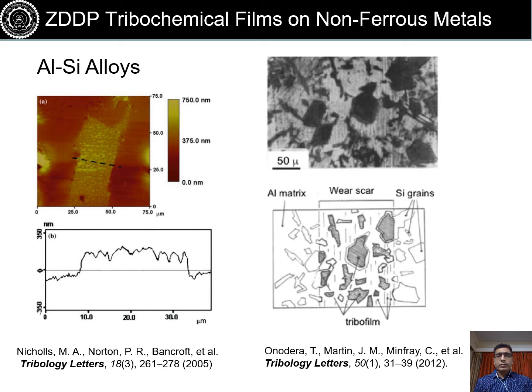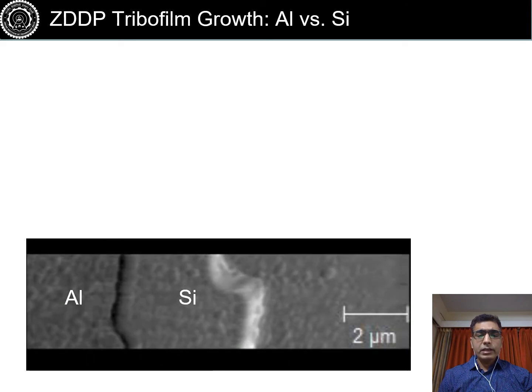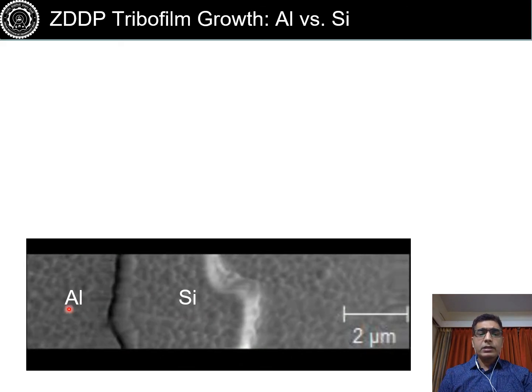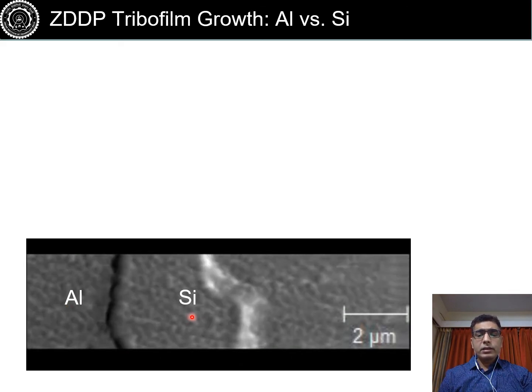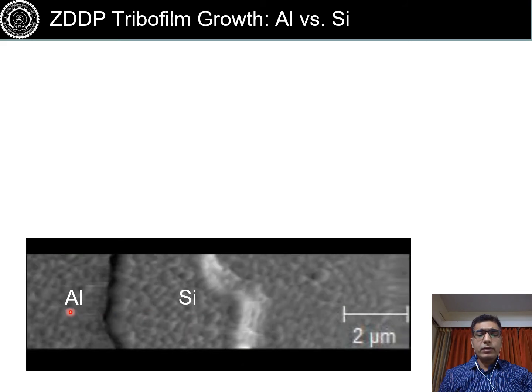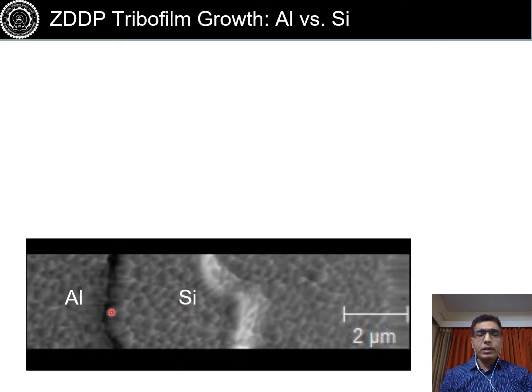There's another set of results which shows a similar observation that silicon is where tribofilms are developing, whereas there is no tribofilm on the aluminum matrix, which is the softer region around silicon. So we did this experiment in a more controlled manner where we selected a region of silicon and aluminum matrix around it and did a simultaneous sliding. When we do simultaneous sliding, actually we were puzzled to see a contradictory result where we see tribofilm developing on both aluminum as well as silicon phase.